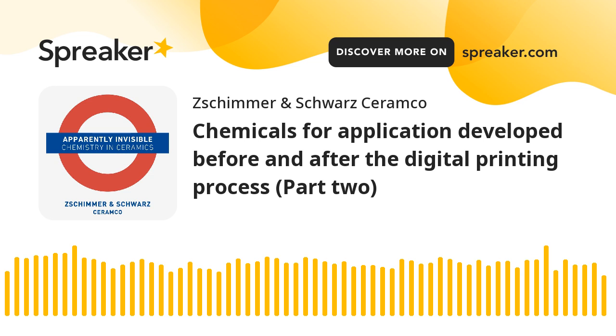We are basically referring to foaming phenomena within the system or to an excessive reduction of the surface tension of the water suspension that results, especially with glazes, in a reduction of the glaze cohesion. So, as you can imagine, we must be very careful because the balance is very delicate. In some other particular cases, due to specific aesthetic projects, repellency phenomena are required. It seems strange, but it's true.